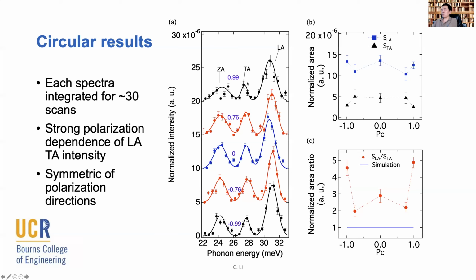Keep in mind, for each side, we are rotating the diamond plates to two different sides. So any inconsistency in terms of the beam geometry or other things shouldn't show up as a symmetric response. So we are fairly confident that what we see is more fundamental to the material, rather than some artifact of the diamond polarizer. And in this case, what we see is